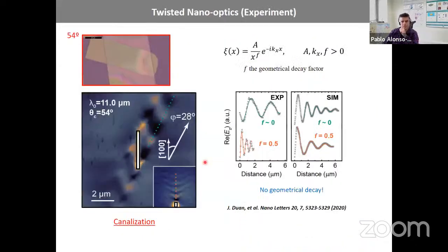It's a very peculiar effect. And what we saw, when we studied the decay of these waves propagating along this direction, is that they had no geometrical decay. Normally when you have a cylindrical wave, it goes in all directions, so it has some geometrical decay: you lose energy over the 360 degrees. But in this case, as it is only one direction, and this is proven by fitting a mathematical equation, we see that there is no geometrical decay. So it goes exactly along one direction.